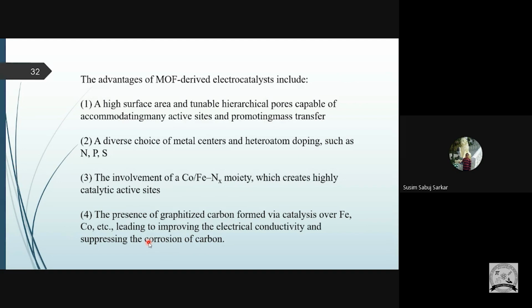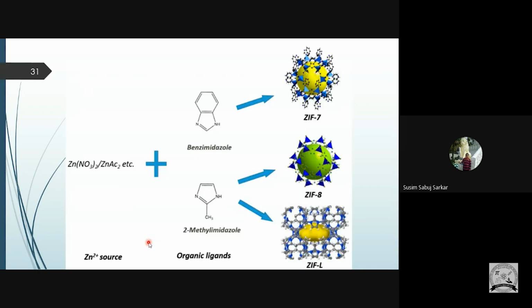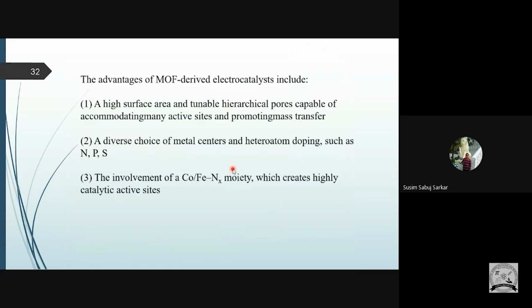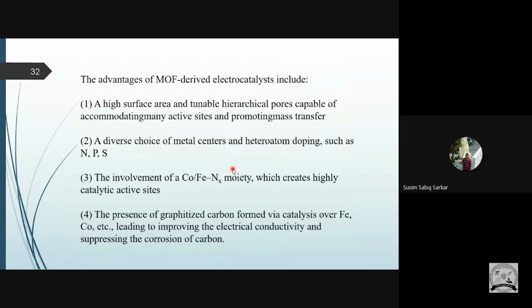That means, as we said, we need at least a carbon framework to make the cathode. So if we form this type of MOF-based catalyst, pyrolyzed with carbon and forming an electrode, then it not only gives very high effectivity, it also reduces the corrosion of the carbon, that means our air cathode. Okay, so these are the benefits of the MOFs.